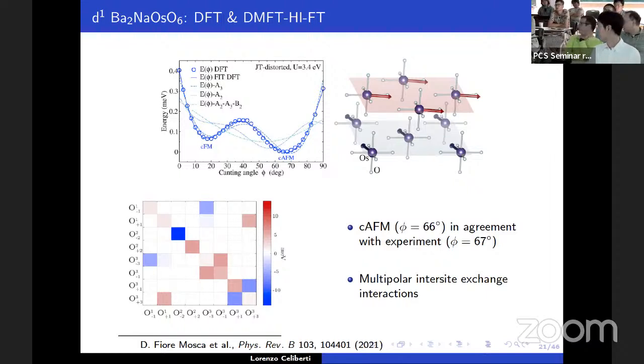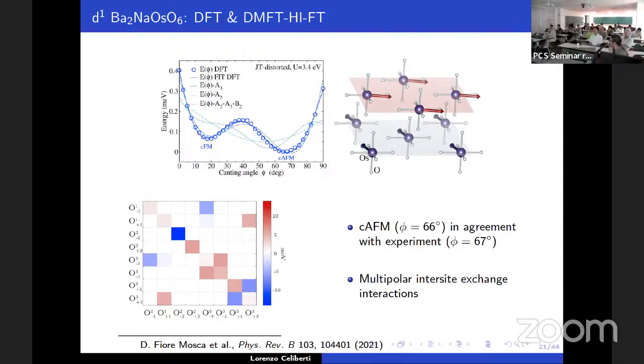But this depends on the interaction. Osmium located in the XY plane, and located in the YZ plane, and in the ZX plane is different, right? This is cubic symmetry and this is a cubic lattice. So this result is for nearest neighbors in the XY plane. YZ and ZX are also rotated by 90 degrees. If I remember correctly, this has been calculated on the FCC lattice with symmetry. So either you take this plane or you rotate, the system should be invariant, right?